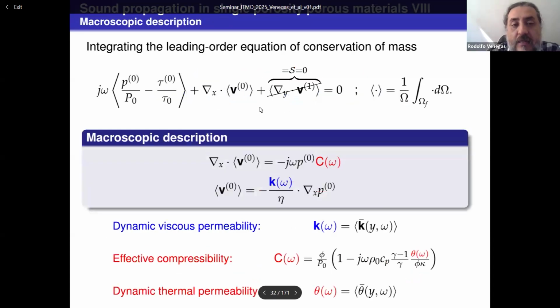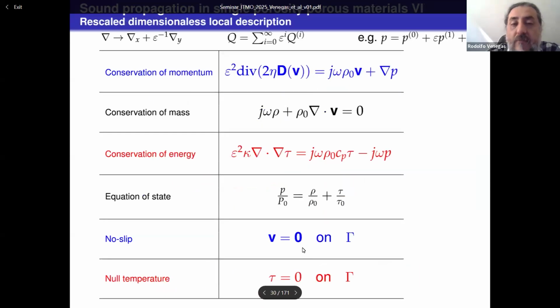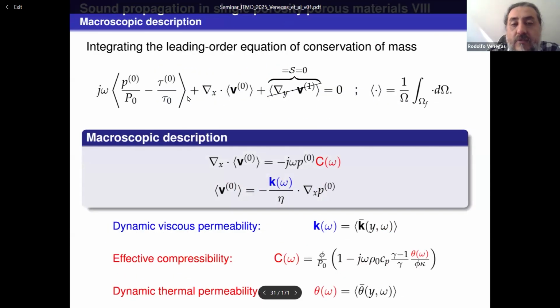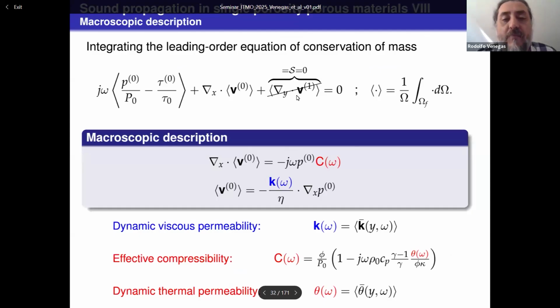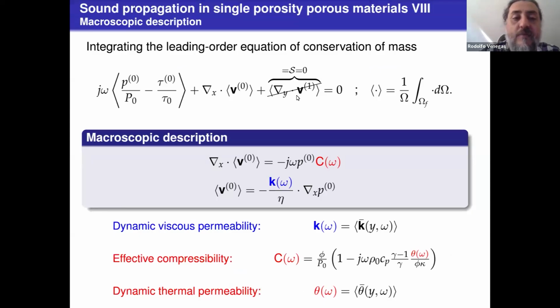But before that, we identify at epsilon 0 what happens for the equation of conservation of mass, and we take the spatial average defined by these brackets in this way, with respect to omega f, the porous space, where omega is the volume of the representative elementary volume. In particular, this source term becomes equal to 0 because the velocity is equal to 0 on gamma. And this is important because later, when we will see other problems, this is not going to be the case. This source term will help us to link the multiscale phenomenon.